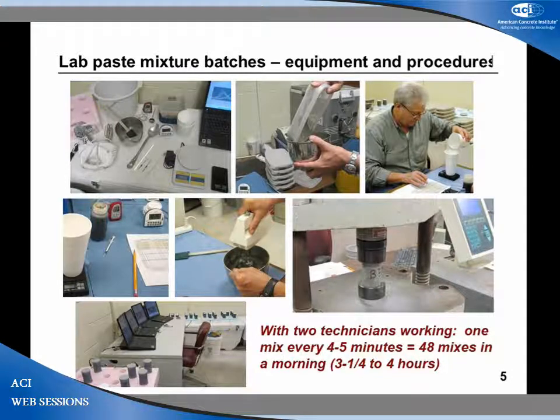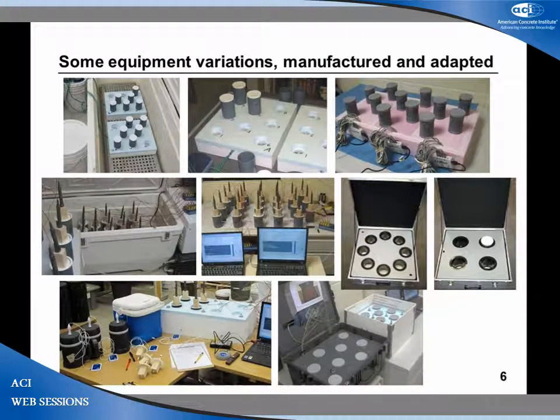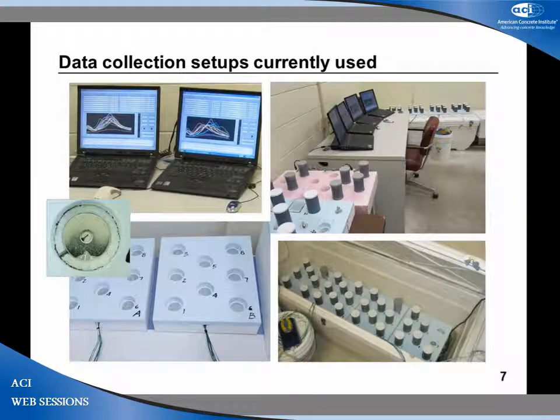There are some variations in the equipment. There's actually some commercially manufactured devices that are related to this, the ADECAL type device that can document thermal profiles for mortar and for concrete. But we've evolved a little bit over the years. We initially started this with probe-type thermocouples. What we're actually using now are simple blocks with twisted wire solder tip thermocouples. You can also use thermistor-type temperature sensors that are in a foam block exposed to the bottom of a 2x4 cylinder that's isolated from the air with a thin layer of insulation with a 2-inch cutout.